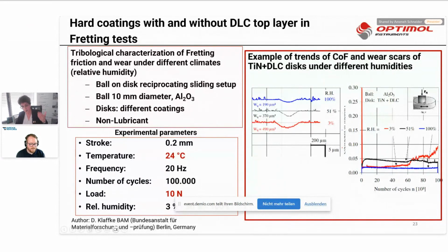The ball was 100Cr6 or aluminum oxide, and there was no lubricant, a dry system. His parameters are a little different from the standard: 0.2 millimeter stroke at room temperature, 20 hertz, and a much lower load than we are used to with a lubricated system, only 10 Newton here. And he has 3 different relative humidities, 3%, about 50%, and 100%.